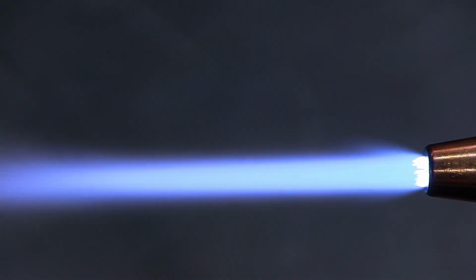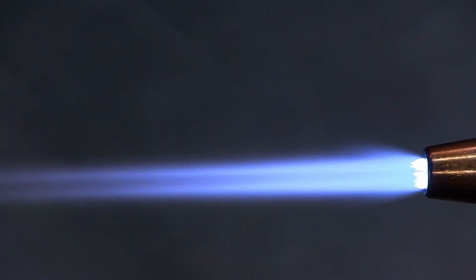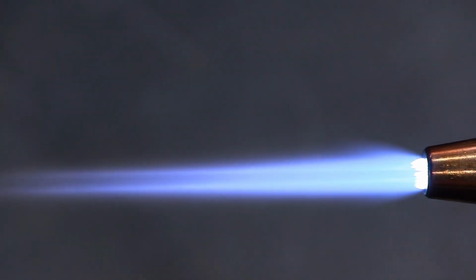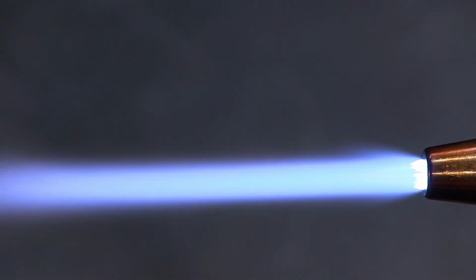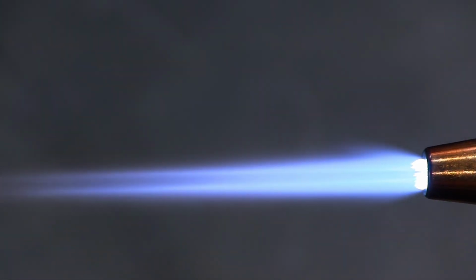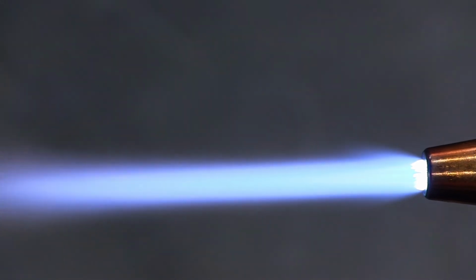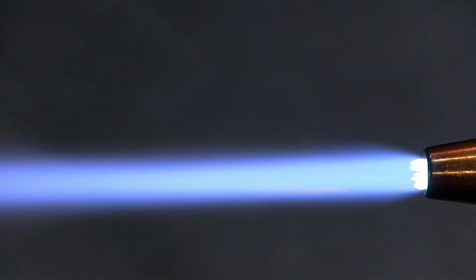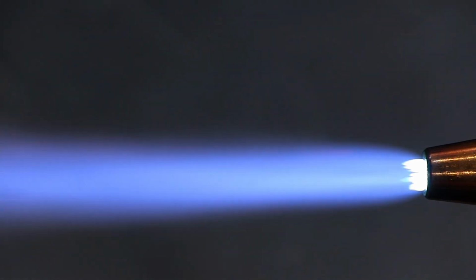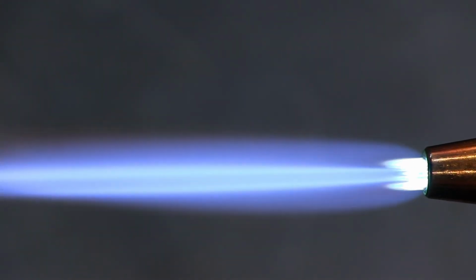A good indication of that is you start getting a very, very specific glow, and when you hit that cutting oxygen, it should form a nice straight jet, as straight as possible, as long as possible, as even as possible. If, when you hit the cutting oxygen, the core of the flame and those widest parts do not move, that means you're just a little bit too much on the oxygen side.